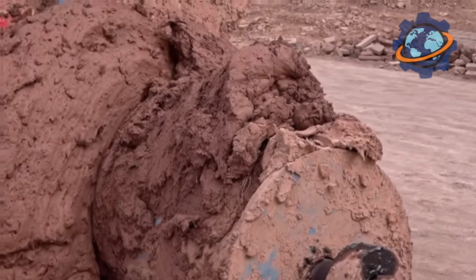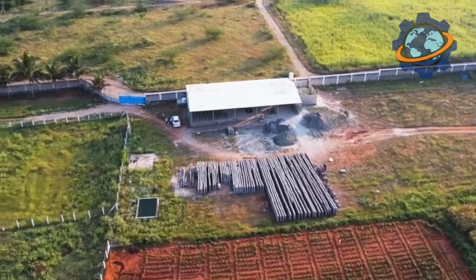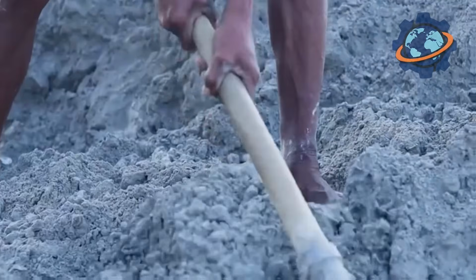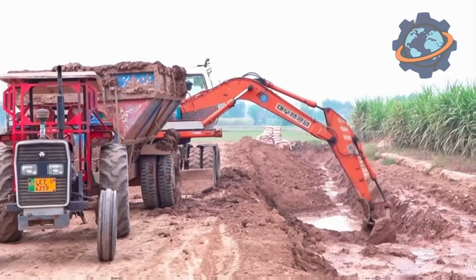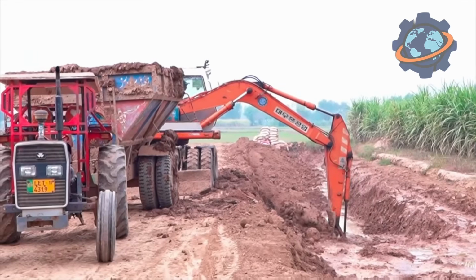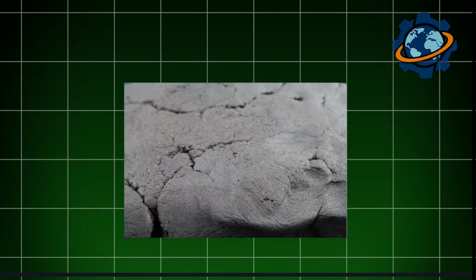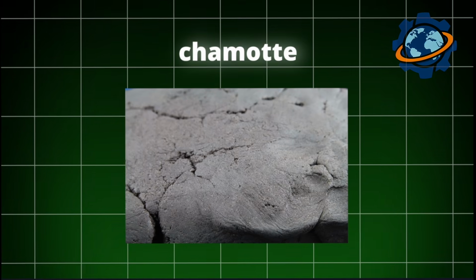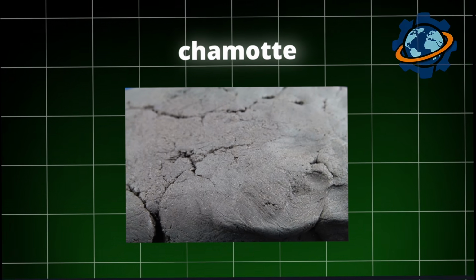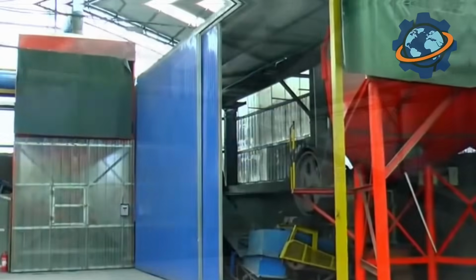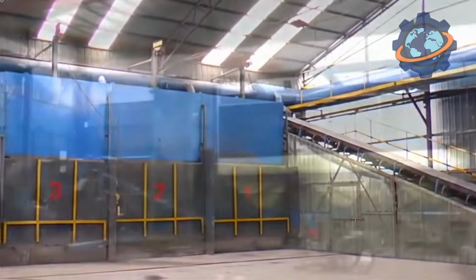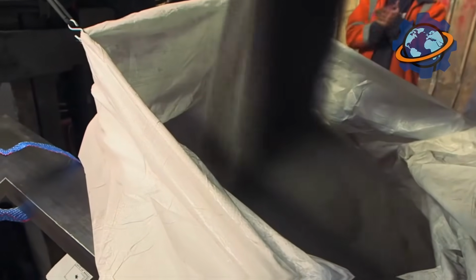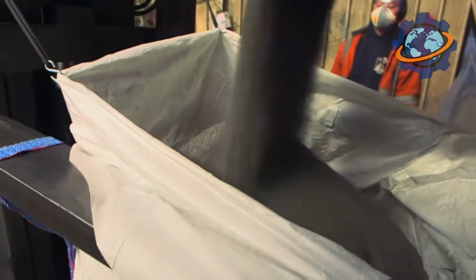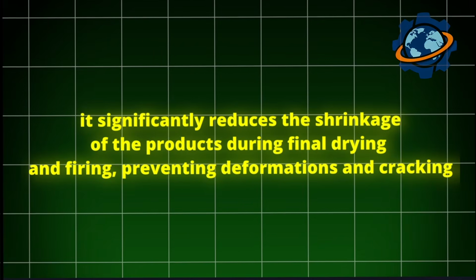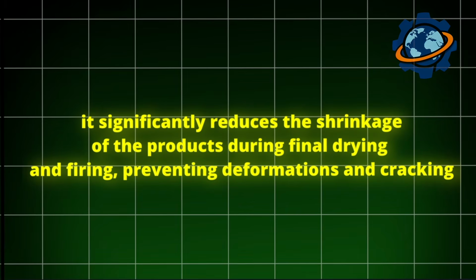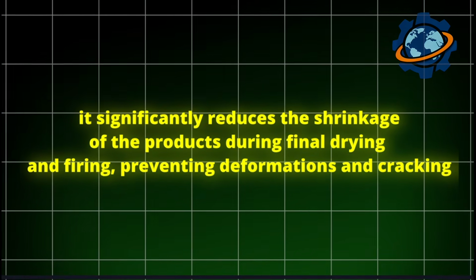To give the future product stability and predictability, manufacturers resort to a technological trick. Part of the mined clay is not sent directly into production, but is first fired in kilns at temperatures up to 1,500 degrees Celsius. As a result of this process, the clay loses its plasticity, sinters, and turns into a very strong, stone-like material called chamotte. This finished chamotte is then crushed and used as the main component, with a certain amount of fresh, plastic clay added to it, which acts as a binder. This approach solves a key problem. It significantly reduces the shrinkage of the products during final drying and firing, preventing deformations and cracking.